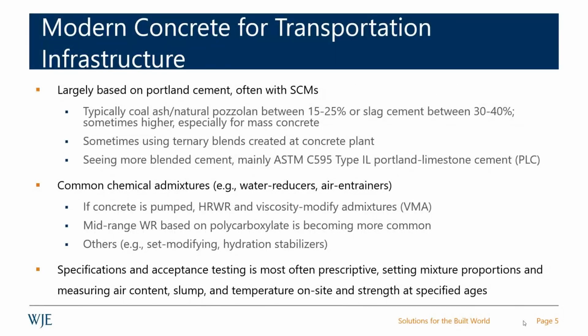So basically, just very, very quickly, modern concrete that we use in our transportation infrastructure. Typically, we're using coal ash or natural pozzolans between maybe 15 and 25%, or slag cement, and I notice that's in some of your specs now, typically between 30 and 40%. So this is commonly added at the concrete plant. Sometimes we're using ternary blended cements, or even other blended cements, such as Type IP, which is becoming common out west in some places. The Type IL cement really took the country by storm starting in about 2022. It's been used for decades in Europe and elsewhere in the world. And now, as we'll talk about later, most of our cements used in the US are ILs.